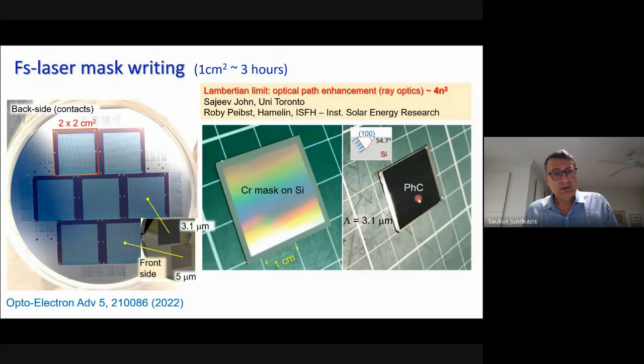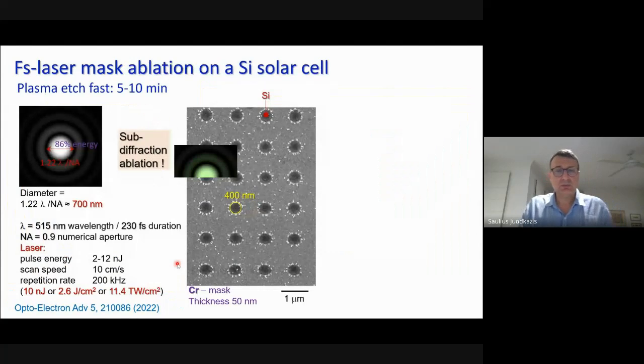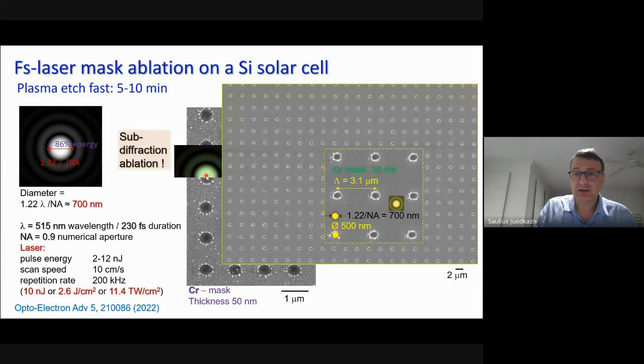On the back side of solar cells, we have all the electrodes collecting electrons and holes. But on the front side, which is shown here, we fabricate those patterns for light trapping. So we start with chromium. A single shot makes ablation, which is subdiffraction limited. And then we fabricate large areas with the design given to us by Sajeev John.